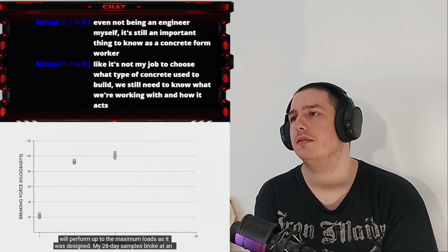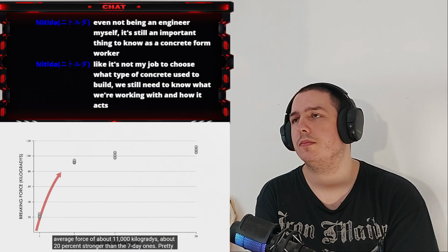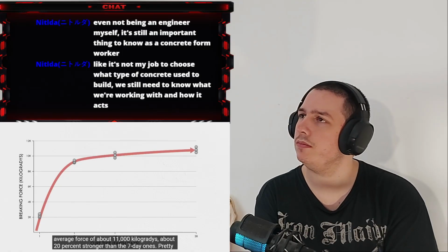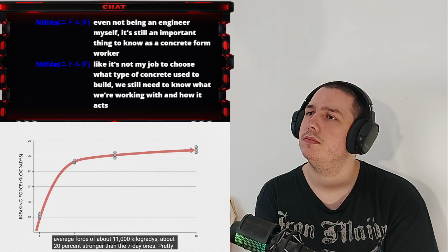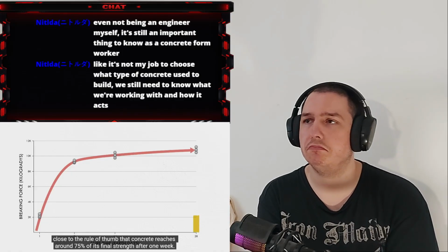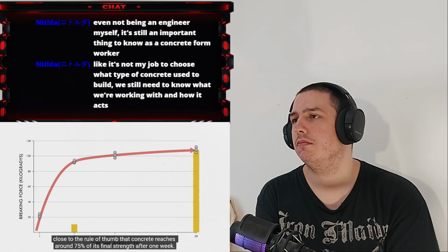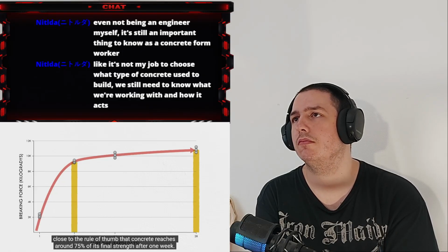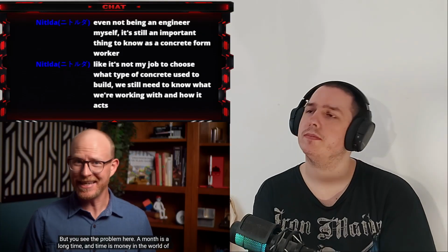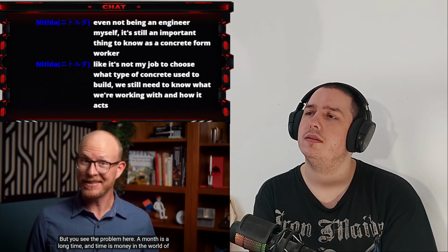My 28-day samples broke at an average force of about 11,000 kilograms, about 20% stronger than the 7-day ones. Pretty close to the rule of thumb that concrete reaches about 75% of its final strength after 1 week. But you see the problem here. A month is a long time.